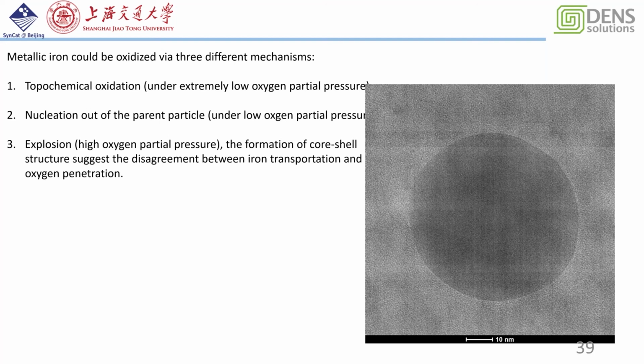But for the medium level of oxidation, this nucleation process maybe happens at about several Pascal. But this really depends on the temperature. That means that at a lower temperature and with high pressure, it can happen. But with a high temperature, like 600 degrees or so, the oxygen pressure should be quite low.